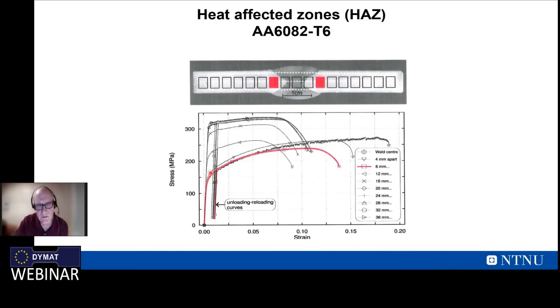So for this alloy, which is a 6082 T6, you lower the yield stress by 50% by moving from the material out here to what happens in the weld. And when you stretch this, this will definitely have an impact on how localization will take place and how your structure will behave when subjected to an impact.